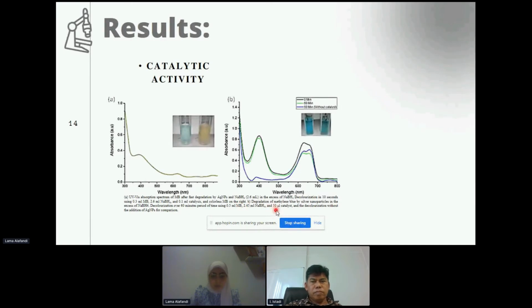It was reduced to 50 microliters of the catalyst to be able to have this curve, so we can understand more the kinetic rate and the percentage of decolorization, and compare it to the results without a catalyst, so we can prove that silver nanoparticles can act as a catalyst. So here, the blue one is without any catalyst, and the green one is with adding a catalyst for 1 hour. So we see that silver nanoparticles worked to speed the reaction and work as a catalyst.